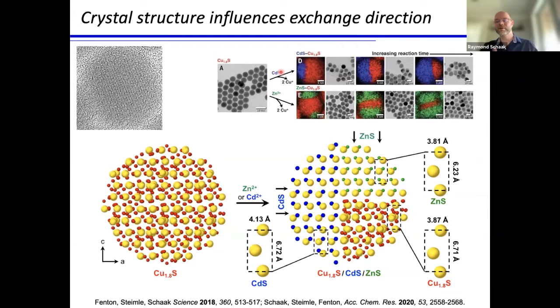And so what that does is it creates preferences within this nominally spherical particle. So for example, the sulfur-sulfur spacings in this crystallographic direction match with copper sulfide better for cadmium sulfide than they would in that direction. And likewise, the spacings of the sulfur anions in the zinc sulfide interfaces best with copper sulfide in this direction. So there's an inherent crystallographic preference that puts cadmium sulfide next to copper sulfide in this direction and zinc sulfide next to copper sulfide in this direction.